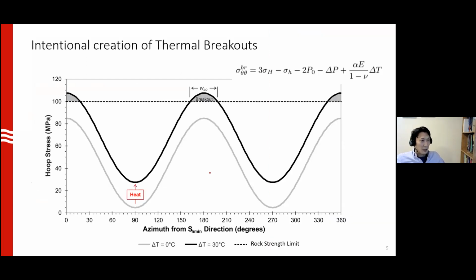The way the concept works is fairly simple. For instance, the first gray line on the bottom may be the hoop stress variation around the borehole, which does not reach the rock strength. The rock strength limit is shown by this dashed line. But if you heat the borehole and create an additional hoop stress due to the thermoelastic stress, you can raise this entire sinusoidal curve so that the maximum hoop stress reaches the rock strength and therefore creates breakouts.